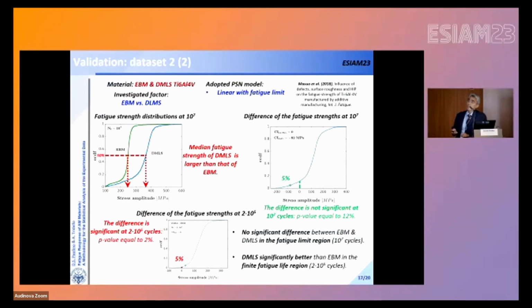And as you can see, the DMLS exhibits a larger median fatigue strength with respect to the EBM. But if we consider the difference between these two distributions, then the difference between the two fatigue strengths is not significant at 5% of error. What happens instead if we change the number of cycles to failure? Instead of using a reference fatigue strength at 10 to the 7, we perform the same analysis at 2 times 10 to the 5 cycles. And in this case, the difference was significant between the two fatigue strengths.